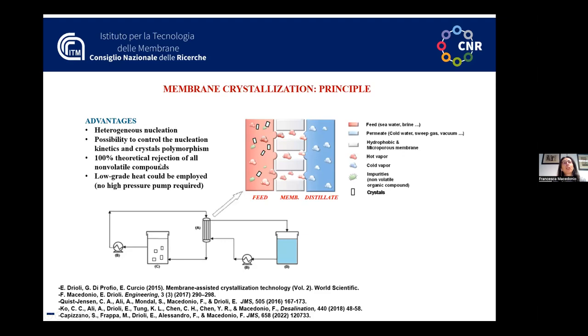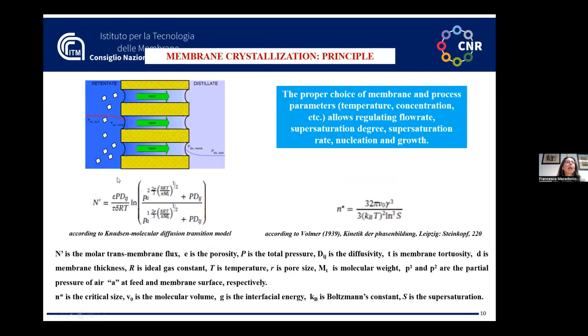In particular, we have a rejection of almost 100%. This means that we can have very high purity water on the permeate side. Moreover, in the case of membrane crystallization, the solvent transmembrane flux can be regulated very precisely through the proper choice of membrane structure and operating conditions. Depending on pore size, membrane porosity, and the temperature and pressure of the process, we can regulate the solvent transmembrane flux. This means that we can regulate the supersaturation rate and then finally the formation of the crystal nuclei.